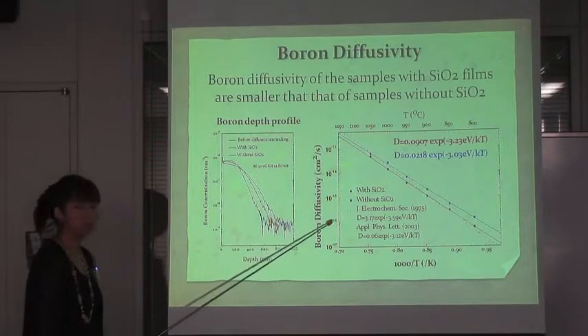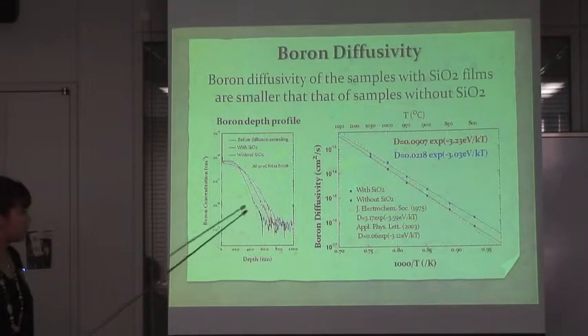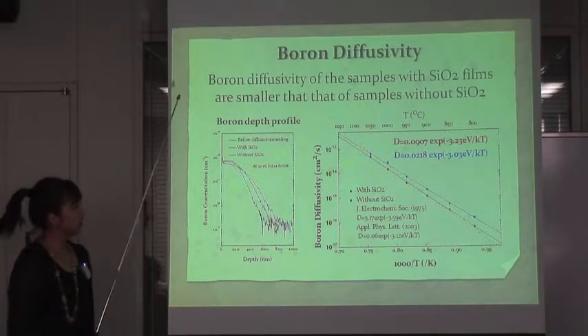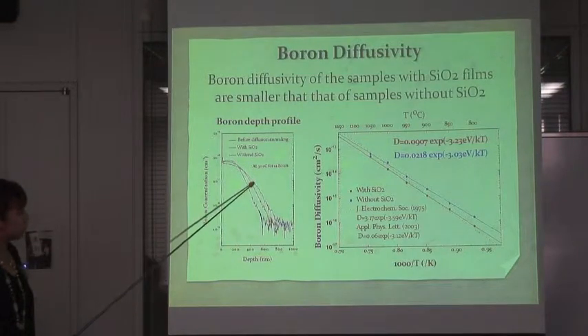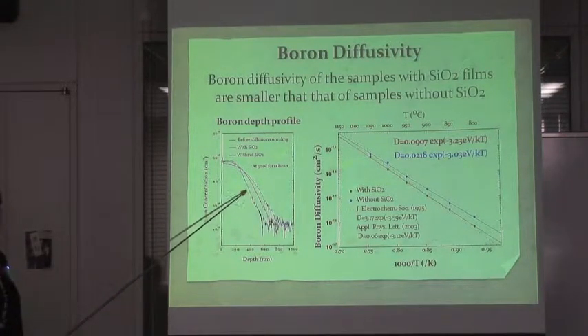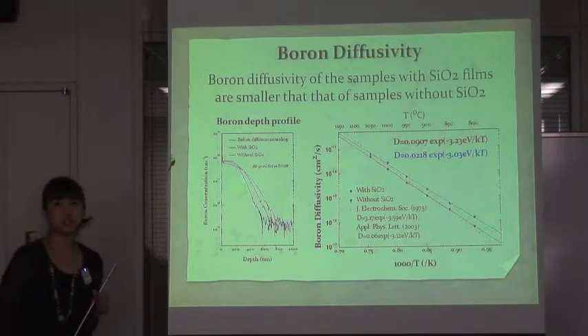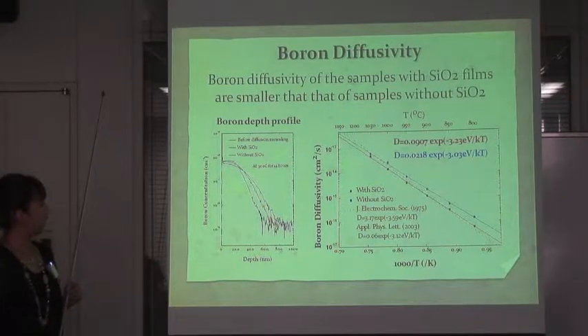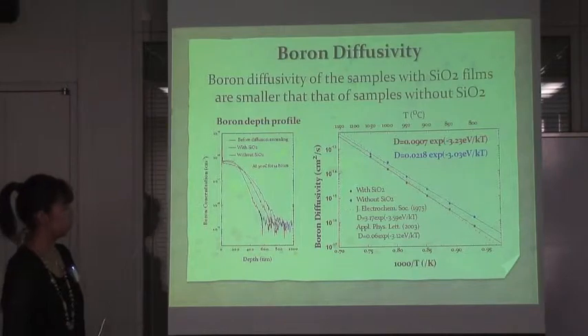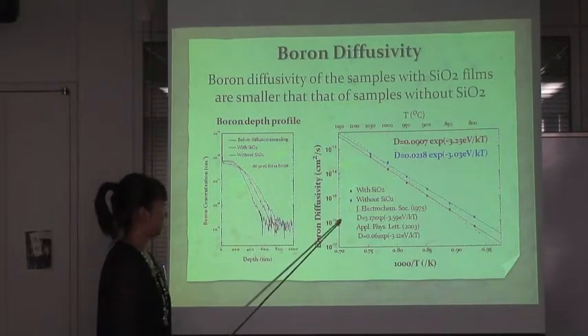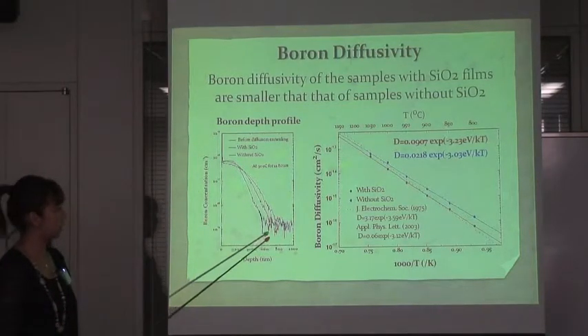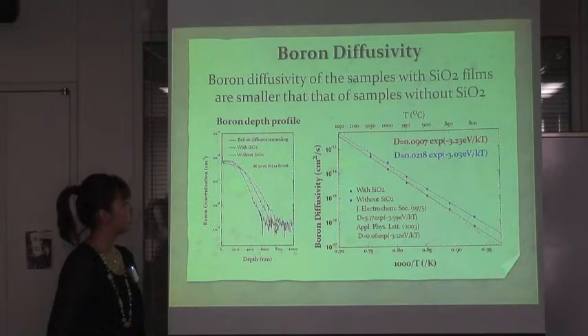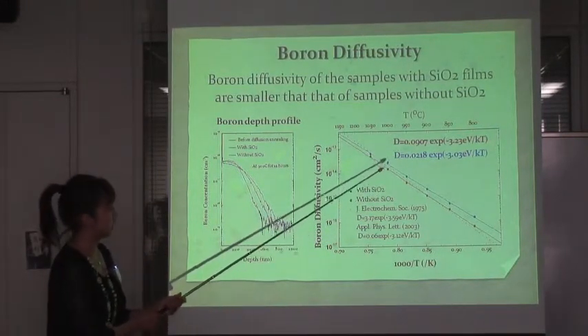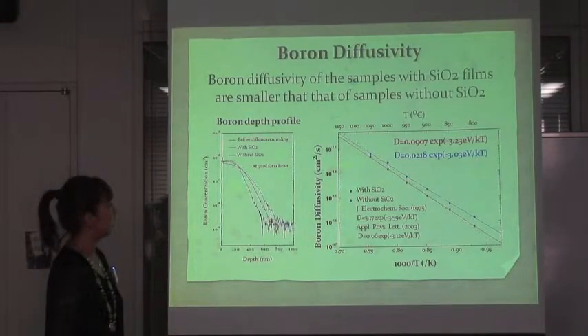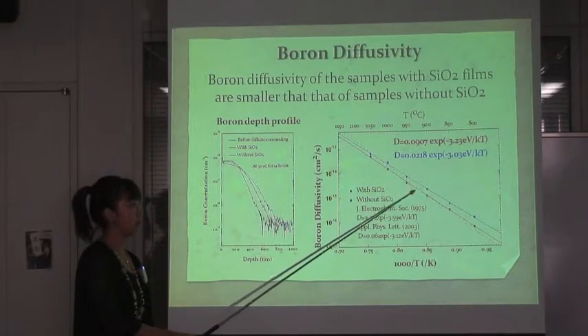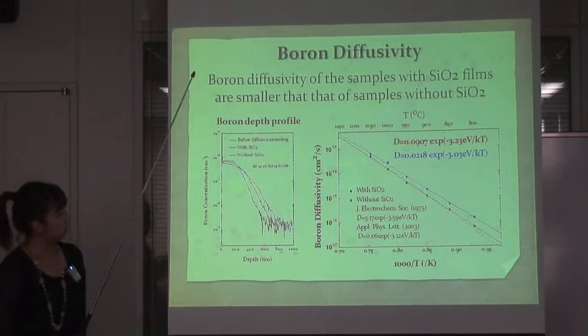And this figure shows boron diffusivities obtained from the depth profiles. Boron diffusion in the samples without silicon dioxide was larger than that in the samples with silicon dioxide, and this tendency was consistently obtained for the different diffusion annealing temperatures. This is boron diffusivities from these depth profiles as a function of the inverse of diffusion temperature. Red is with silicon dioxide, blue is without silicon dioxide, and we obtain different diffusivities between the two kinds of samples.